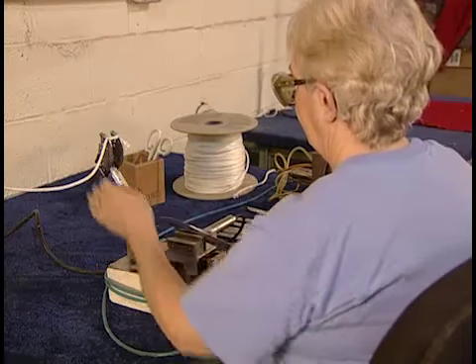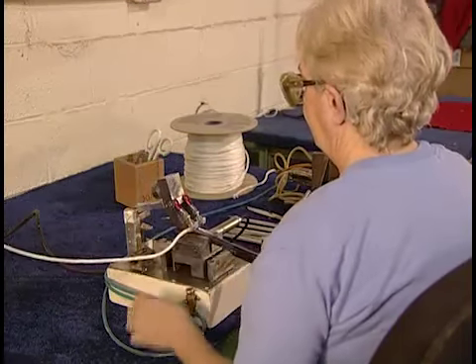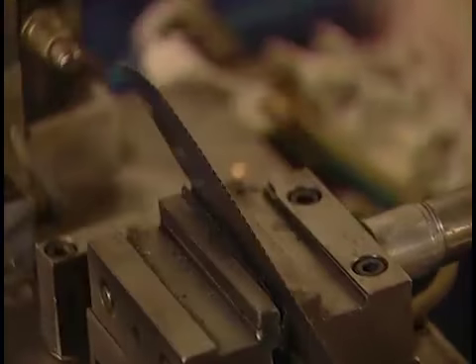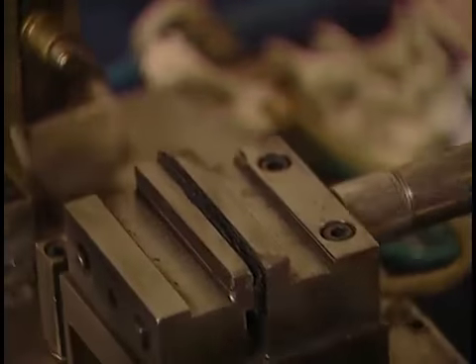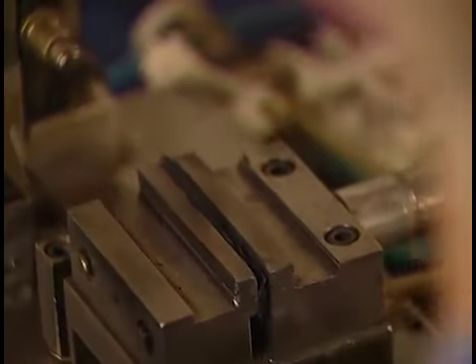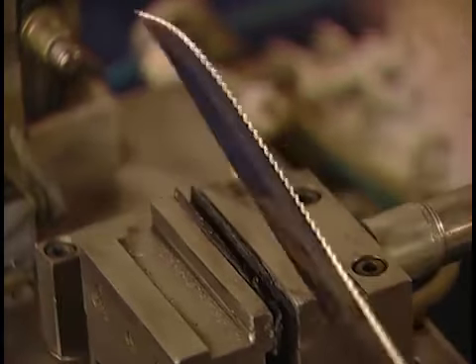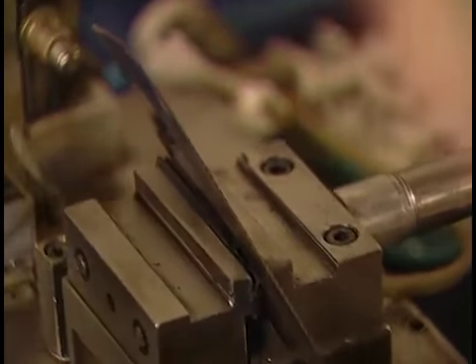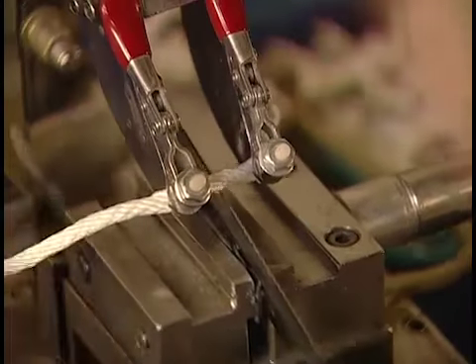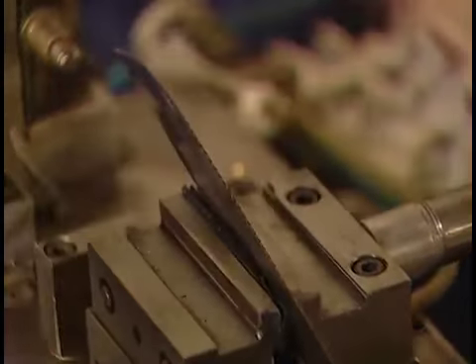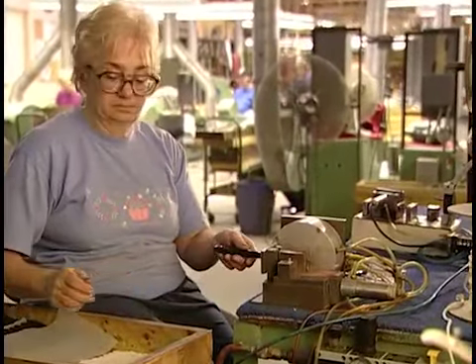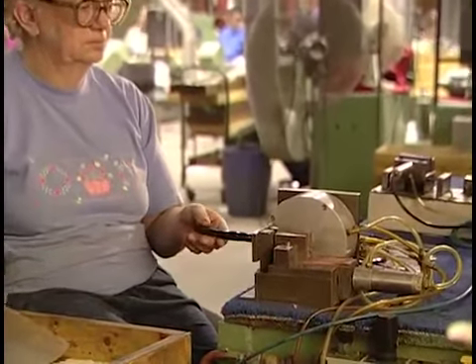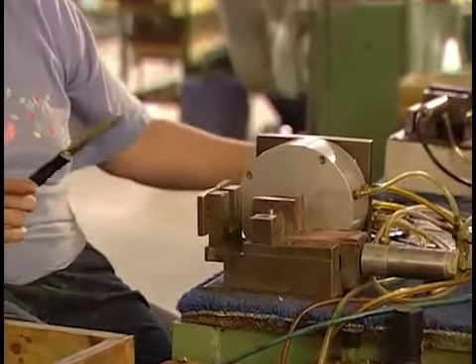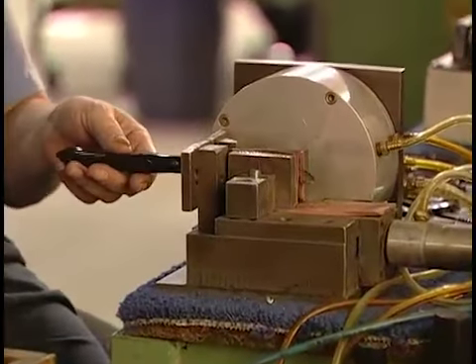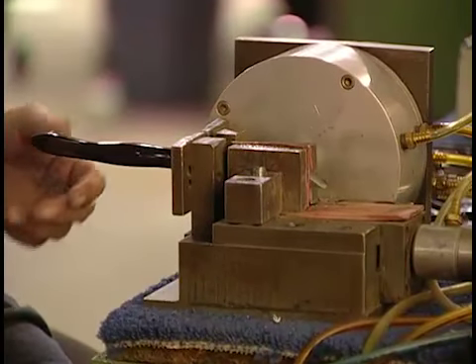Because sharpness is so important to Cutco, we conduct a very special rope test for edge sharpness. To pass the test, a Cutco knife must be able to cleanly slice through a 3/16" nylon rope in 3 strokes or less. Almost always it takes only 1 or 2 strokes. Another evaluation is the 100-pound test. The machine cylinder exerts a force of 100 pounds in an attempt to pull the blade from a solid handle.